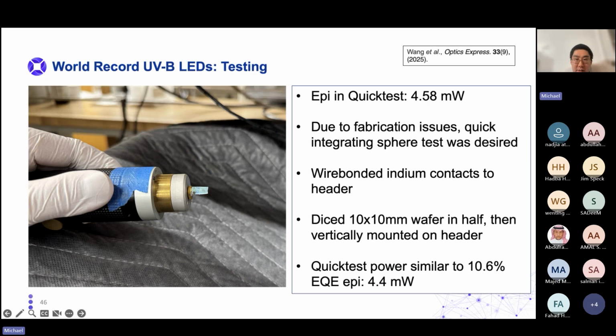So this is a test setup that we see with the indium contacts. And in quick test, it was 4.58 milliwatts. What I did was, because of our fabrication issues that we're currently working on, I just took the quick test epi with the indium contacts and wire bonded the indium to a header, and then just mounted it into the integrating sphere to test.